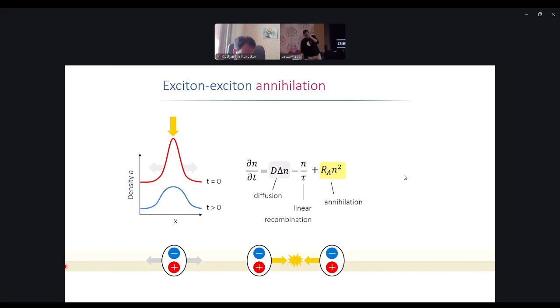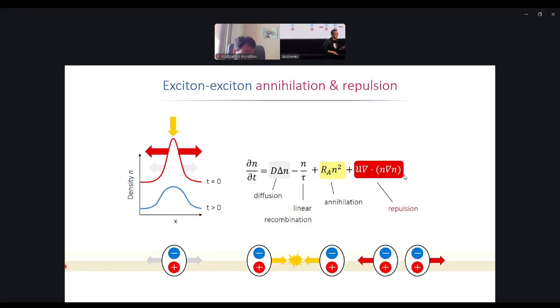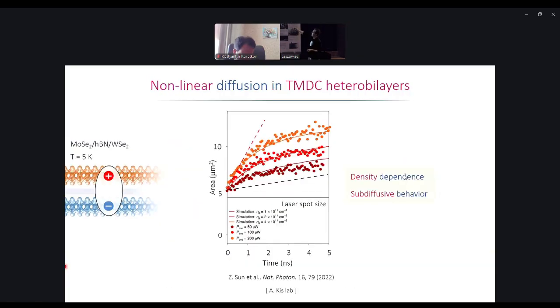Yes, but for a biexcitonic state, it's hard to build a biexciton state from these two dipolar excitons. But the repulsion can be not trivial to handle also theoretically, because usually one also needs to go beyond this classical description. But in principle, in this case you can expect, again, a density-dependent term, which will give you a current of the excitons due to the repulsion. And this indeed was observed, or the data was interpreted like this.